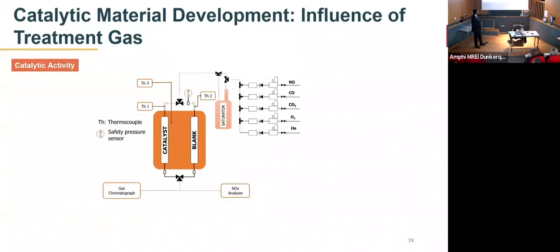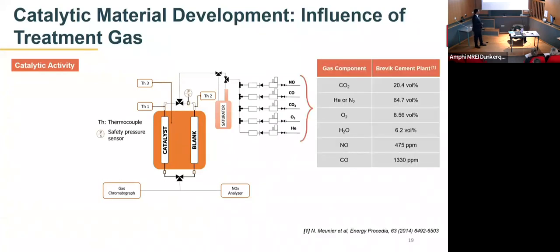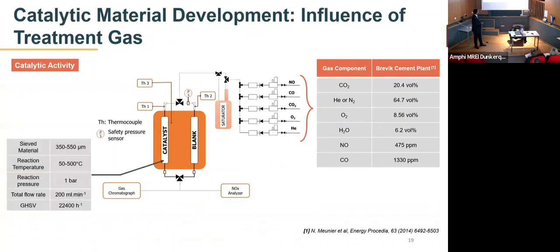After completing the material characterization, we compare the catalytic performance of the different mixed oxide samples. For this, we utilized a lab scale reactor. The gas composition that we utilized was adapted from a flue gas from the Brevik cement plant. The catalyst that we used is in sieved form, with a size of 350 to 550 micrometers. We use light-off curves, so we operate between temperatures of 50 to 500 degrees Celsius. We work under a reaction pressure of 1 bar and a total flow rate of 200 milliliters per minute.